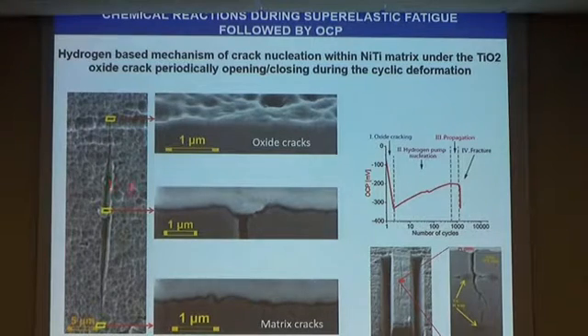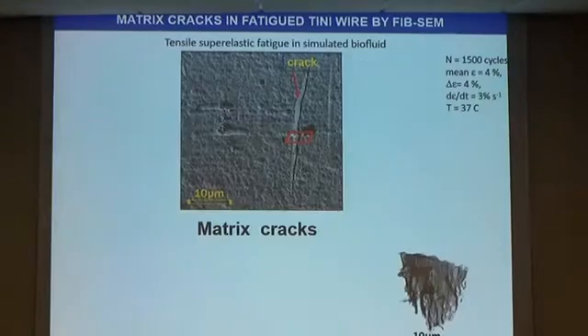This is the crack. We made a FIB cut through it, and we looked at different places, here and here where only small cracks are, and in the center where the big crack is. The small cracks are not in the center at all. But here and here you will find the oxide cracks, and here you will find the matrix cracks, and there is a very good correspondence between them. For me, this confirms that the damage actually comes from the oxide.